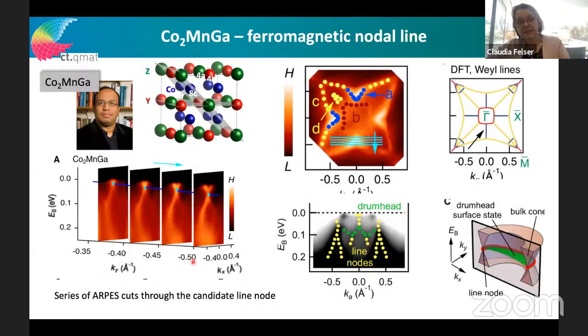Here we investigate the XY plane. The prediction, if you have such a nodal line ferromagnet, was that you would have surface states which are more complex than simply Fermi arcs. You find this kind of drumhead surface state, which is in nice agreement with the calculated prediction of the surface state, which also tells us that a simple density functional theory calculation for the Heuslers works quite well.